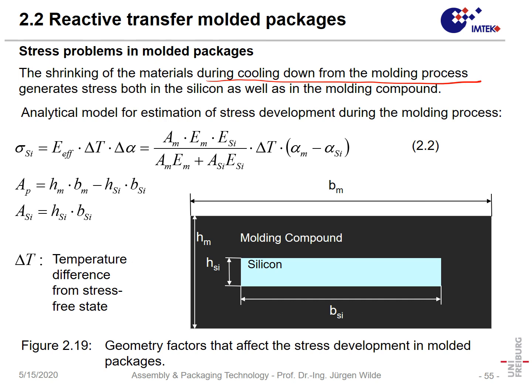And the question is, why does it shrink? So we have seen, for instance, the CTE here is 16, again, ppm per Kelvin. And here, let's say silicon CTE is roughly 3 ppm per Kelvin. And both of the materials, they will shrink, but the molding compound will shrink much more, and so we will get some compressive stress on the silicon. And that stress can be estimated.